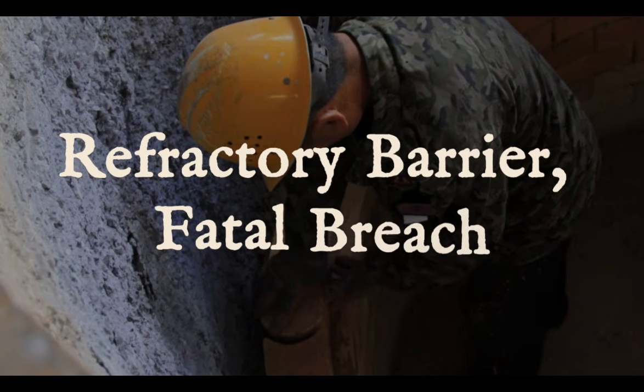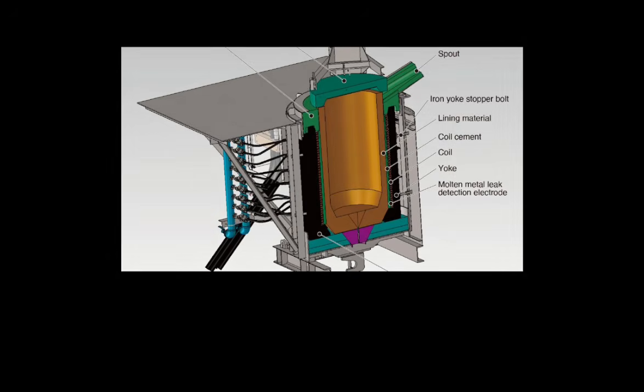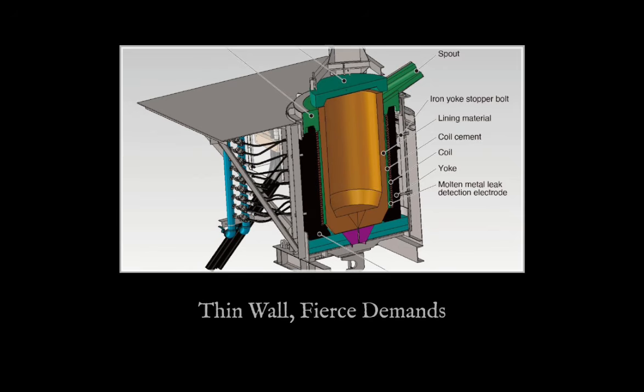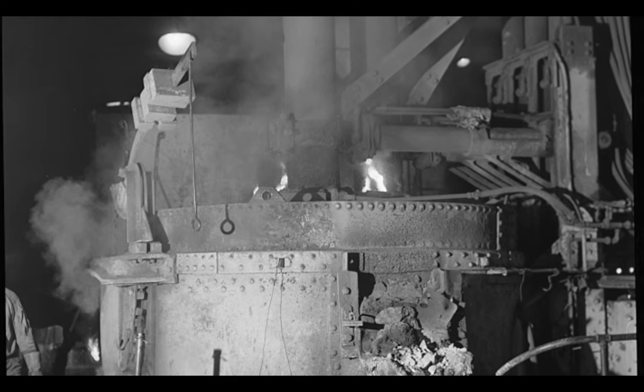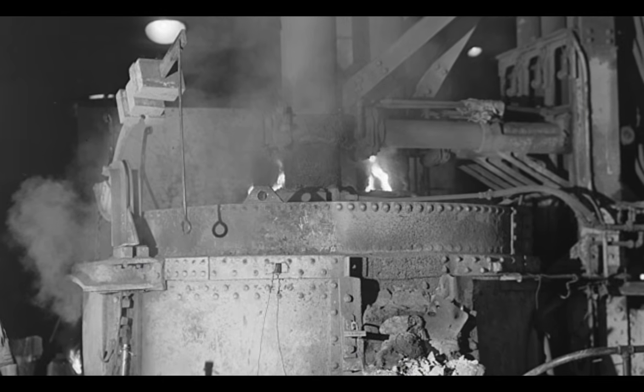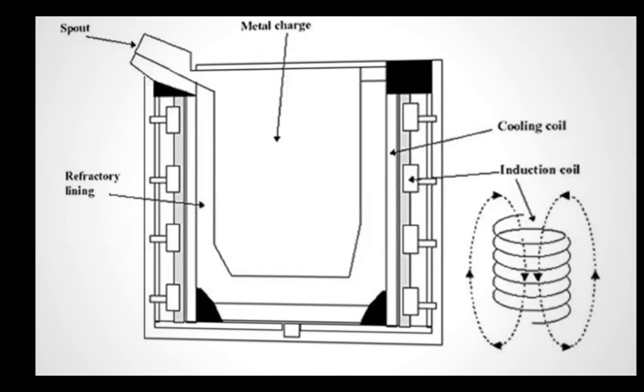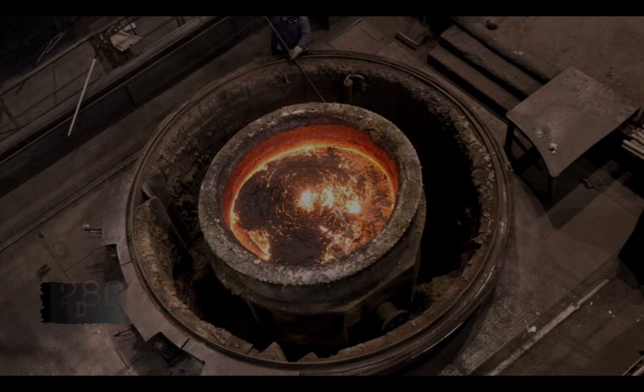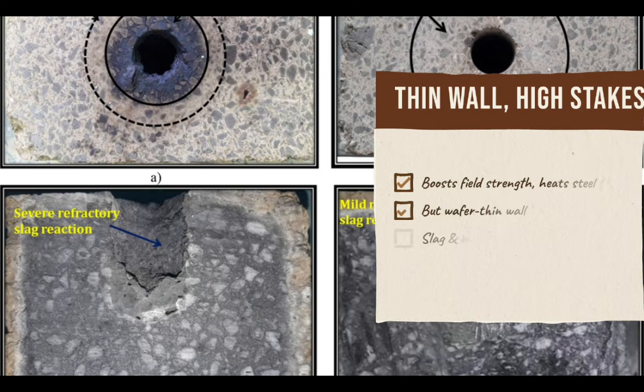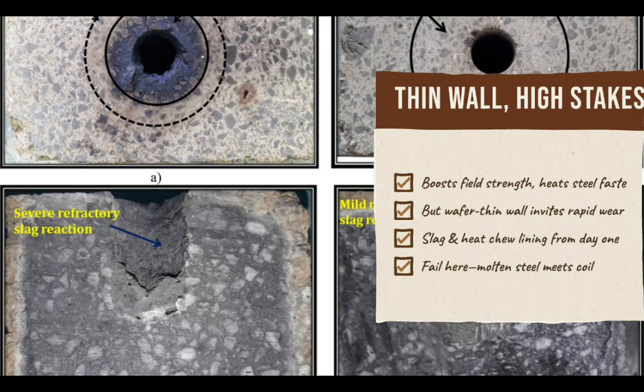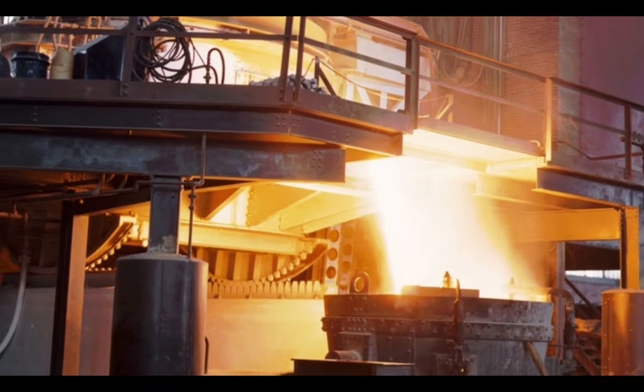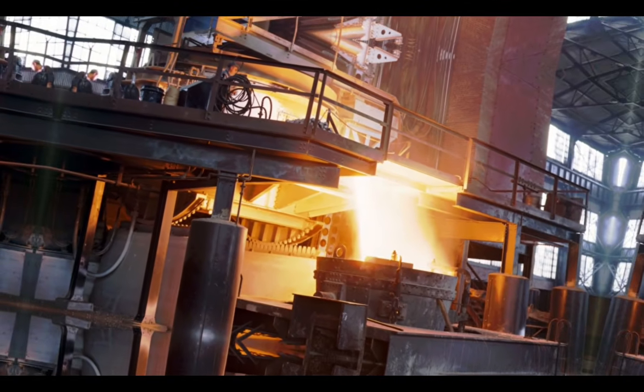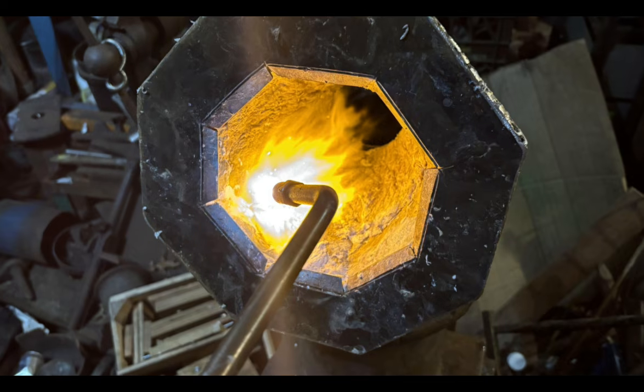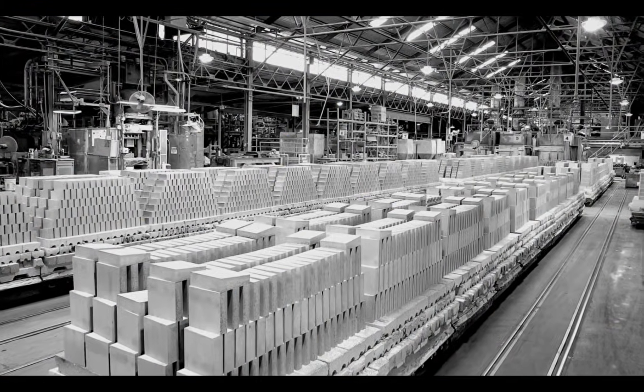Here is what the refractory lining was asked to do. It had to be thin enough that the electromagnetic field could penetrate it without significant attenuation and couple effectively with the metal charge on the other side. The physics of induction heating required the lining to be as thin as practical, but it also had to be thick enough to contain liquid steel at 2,800 degrees against the combined attack of thermal cycling, chemical erosion from slag and impurities in the melt, and the mechanical stress of the charged material shifting and settling during successive heats. The lining was doing both jobs simultaneously, and they worked against each other.